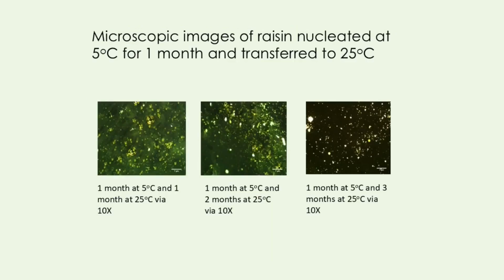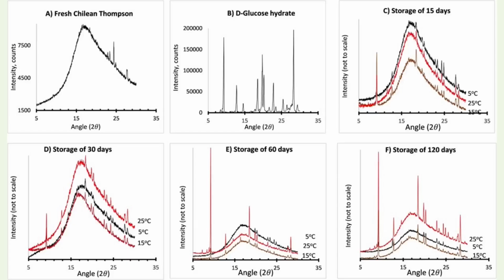So even at 5 degrees Celsius, you don't see any crystal, but when you look under the microscope, you see the crystals. Okay, but it's not coming onto the surface. So just to prove that there are crystals, we worked with crystalline sucrose. We used XRD analysis as well. And then we found that with the Chilean Thompson raisins, not much changes. That was another thing, crystallization.